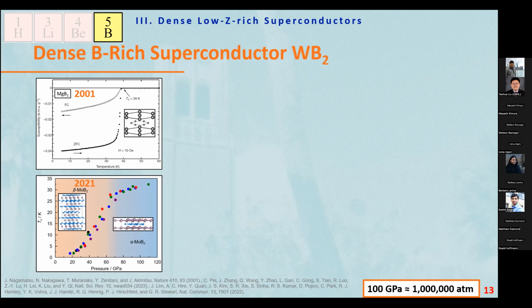And there's a structural transition. There's a buckled layer of boron at ambient pressure. But when you go to a higher pressure, it is very similar to the MgB2-like structure. So there's a layer of boron and then molybdenum layers. So this got our attention for other diboride superconductor candidates.